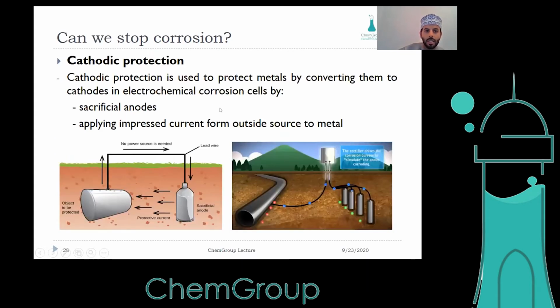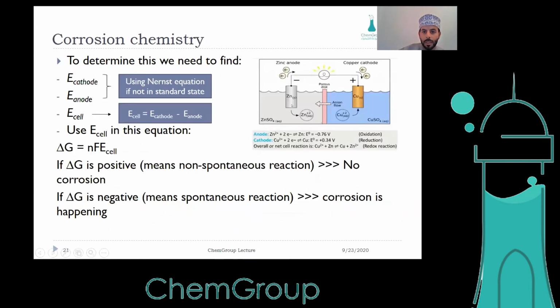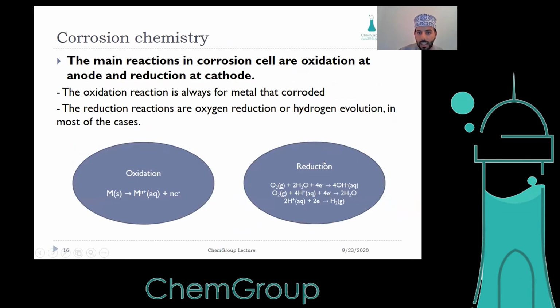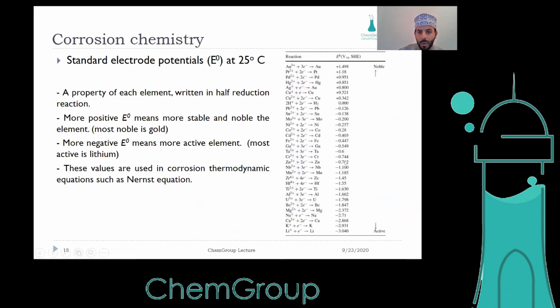Cathodic protection is used to protect the metal by converting it to a cathode in the electrochemical corrosion cell, by sacrificial anodes or by applying current from an outside source to the metal. For example, the sacrificial anodes here are usually made of zinc. If we go back to here, we can see zinc is minus 0.76, and iron is minus 0.447. So zinc is more active than iron. So if we attach zinc and iron, that means zinc will corrode and iron will not.